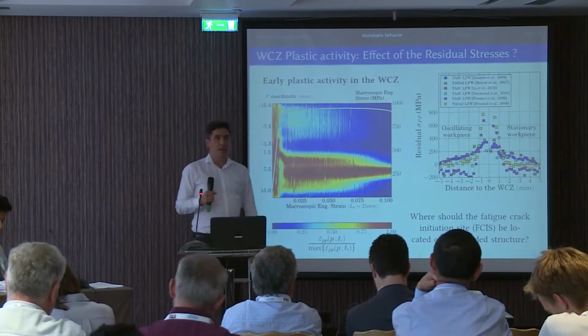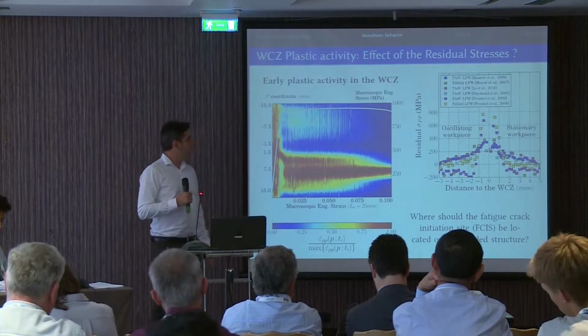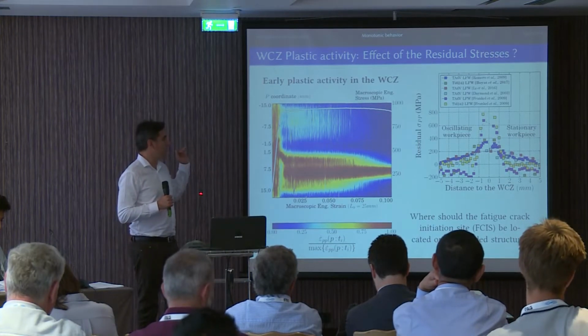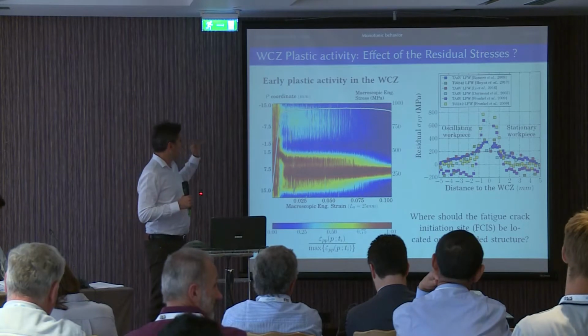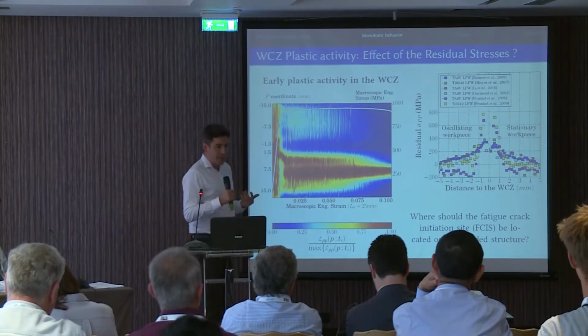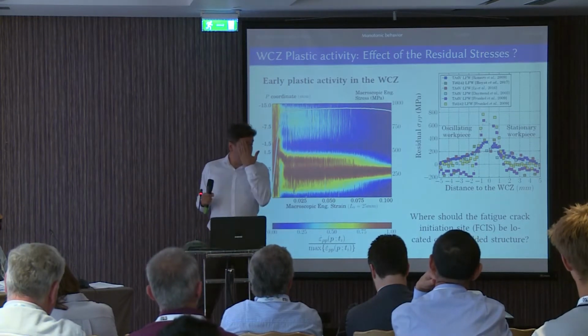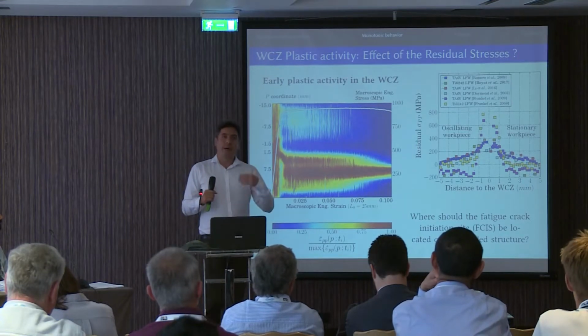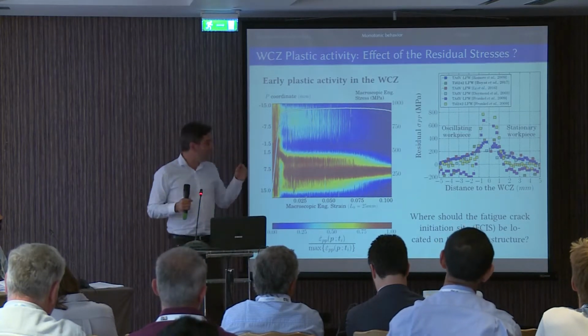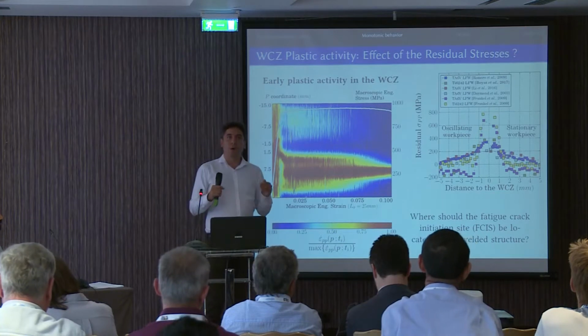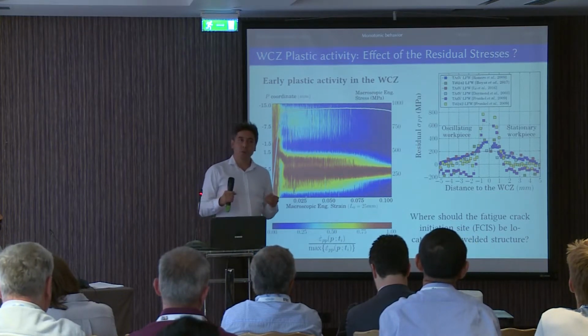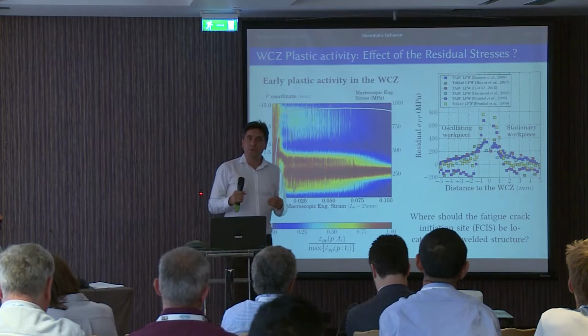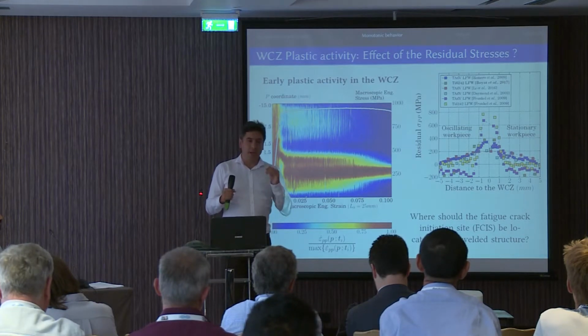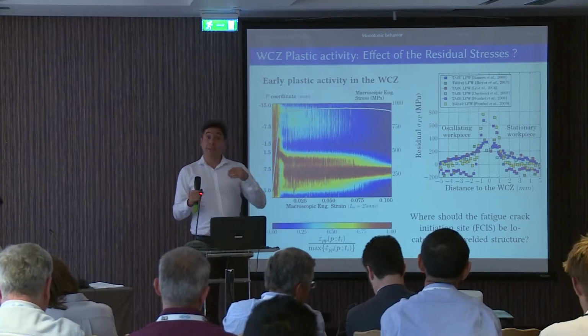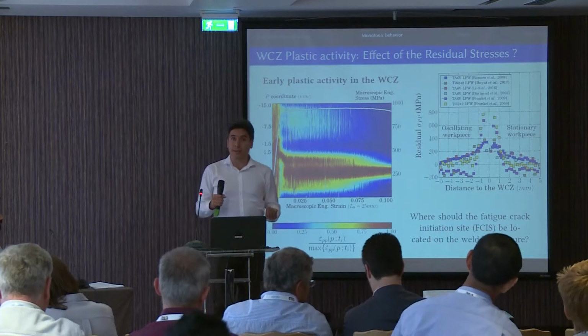As you can see here in literature, we have found a certain agreement about the presence of residual stresses in the weld center zone. But a more interesting question could be asked: now that we have established the localization of the first steps of plastic activity, we should wonder, where do the fatigue crack initiation sites take place during a fatigue test?